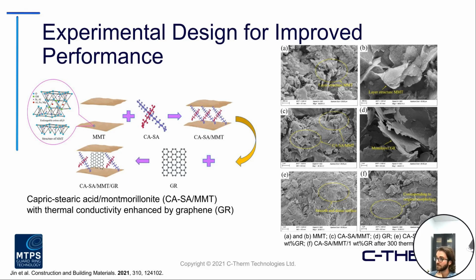We can see some of the SEM imaging on the right there. The top two show the MMT structures. It gets more interesting when you look at the C picture, middle left. That's the incorporation of the PCM MMT composite. You see the graphene monolayer to the right of that. And on the bottom, what they're finding is that when you incorporate all of these materials together, it's small writing there, but a smooth and dense surface. That's a really good indicator that the PCM is going to be well contained inside of that composite material.